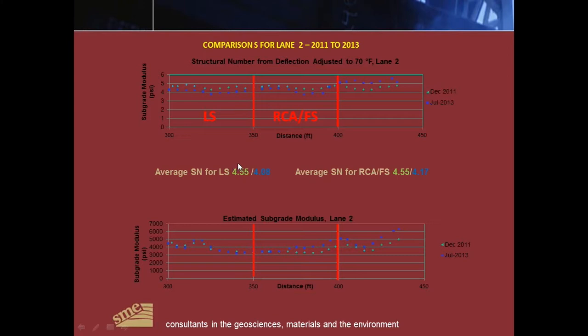Again, the average structural number for the paving sections for both lanes was 4.55 for both the recycled blended material and the limestone, but you can see that there was a slightly greater decrease in the structural number for the limestone section over 2 years as opposed to the recycled concrete foundry sand blend material. It shows that comparatively both these materials are functioning as you would intend. The computed structural numbers from the field tests are slightly lower than what the design structural numbers were by calculation, but you can see they're in good agreement with each other.